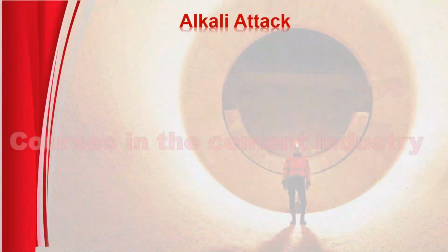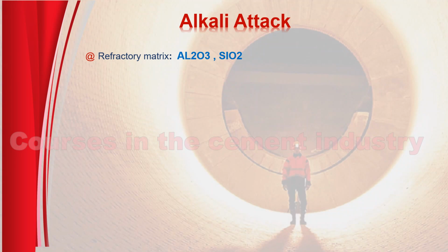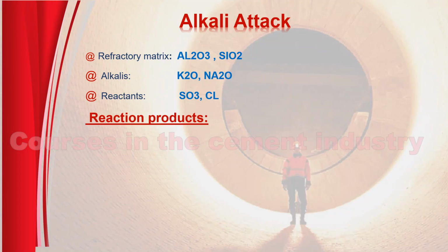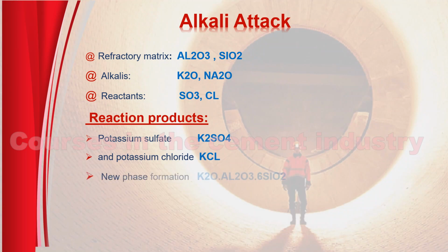Alkali attack. Refractory matrix: Al2O3, SiO2. Alkalis: K2O, Na2O. Reactants: SO3, Cl. Reaction products: potassium sulfate, K2SO4, and potassium chloride, KCl. New phase formation.